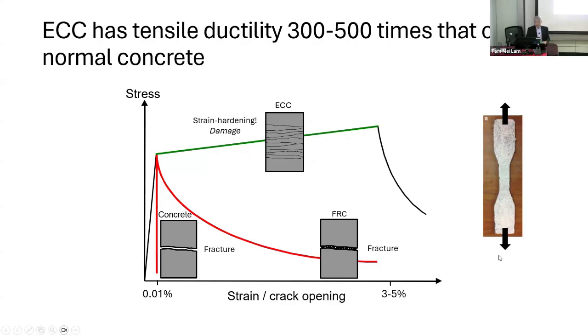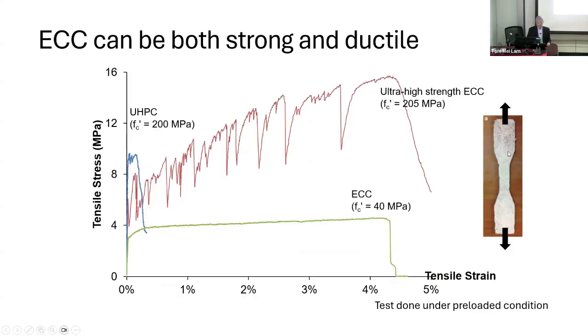And this is because the material can undergo very large deformation. Compared to normal concrete or FRC, it undergoes this softening or sudden collapse at 0.01%. So we are talking about not just a few times more ductile, but hundreds of times more ductile. Okay, so this is what we call tensile ductility, a ductile concrete. We have a stress strain curve that resembles that of ductile metal undergoing strain hardening behavior. All right. So that was an illustration of curves to compare different materials.